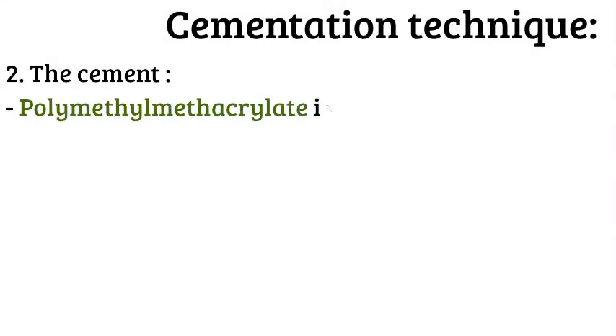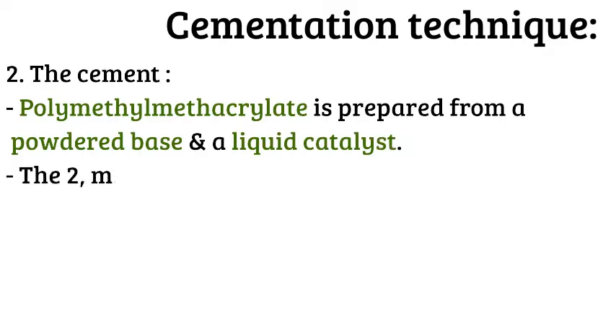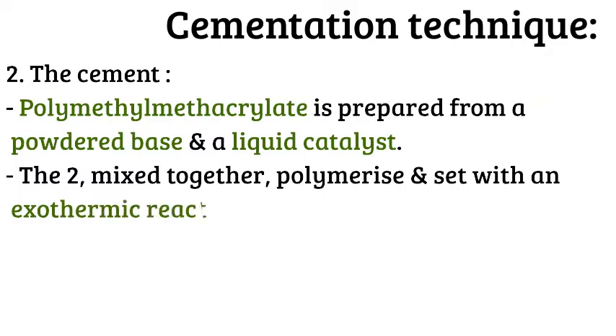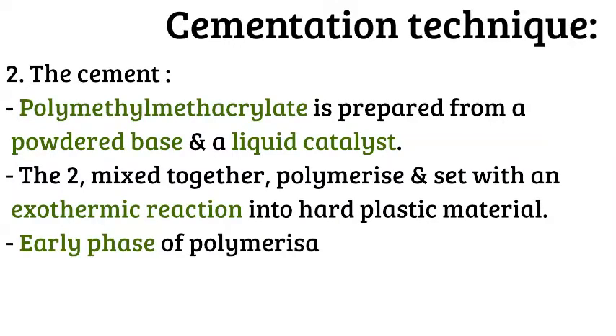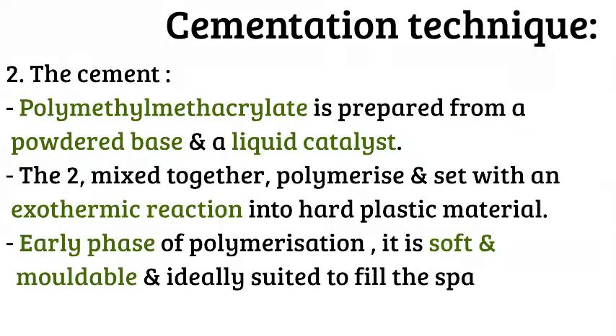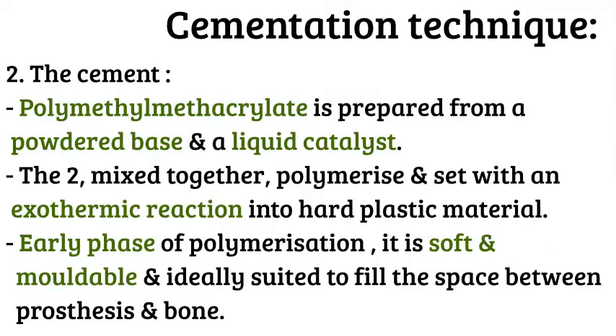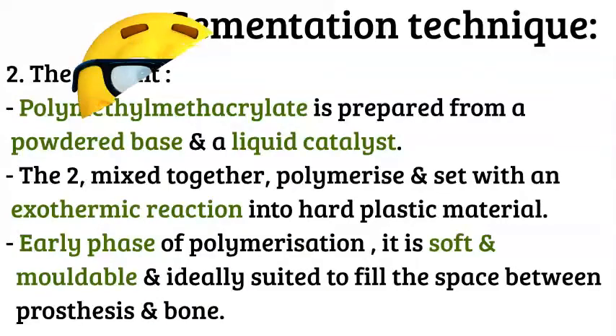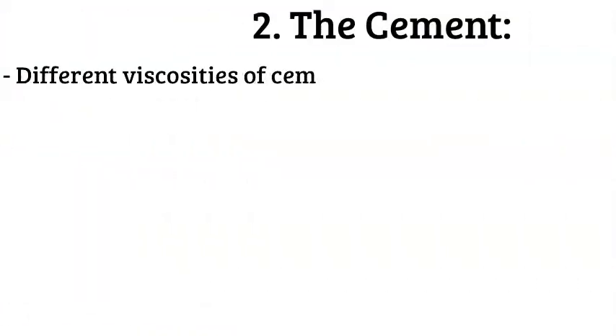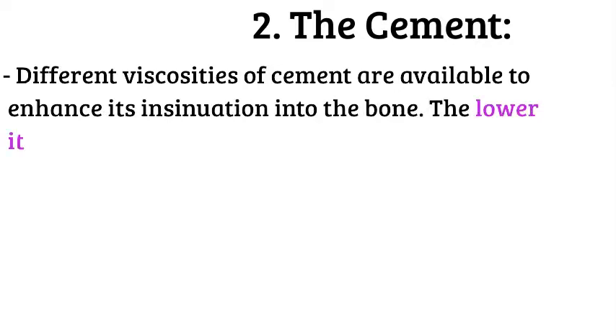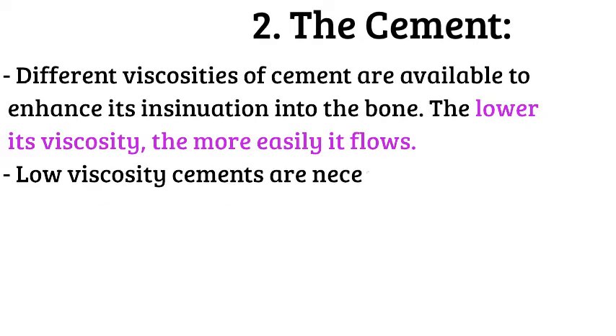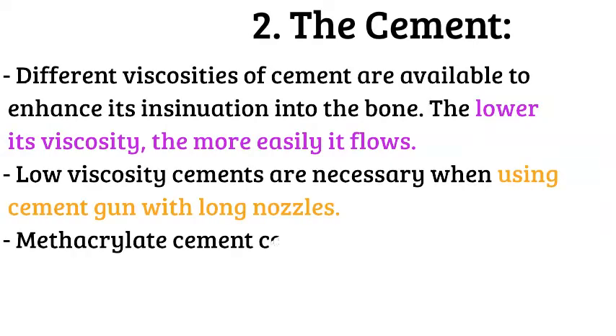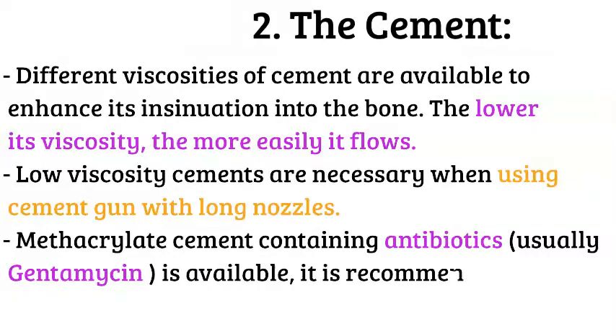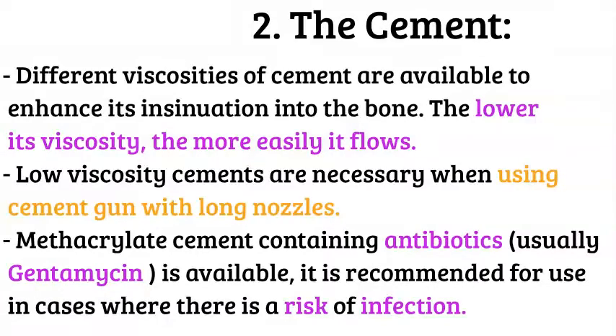Number 2, the cement. Polymethyl methacrylate is prepared from a powdered base and a liquid catalyst. The two mix together, polymerize and set with an exothermic reaction into a hard plastic material. During the early phase of polymerization, it is soft and moldable and ideally suited to fill the spaces between the prosthesis and bone. Different viscosities of cement are available to enhance its insinuation into the bone. The low viscosity cements are particularly necessary when using cement guns with long nozzles. Methacrylate cement containing antibiotics, usually gentamicin, is available and is recommended for use in cases where there is a risk of infection.